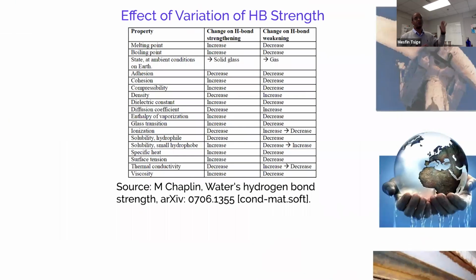So I look at this both on the fundamental side and on the technology side and connect this back to hydrogen bonding. In the case of hydrogen bonding, if we come up with a mechanism of, let's say, increasing the hydrogen bond strengths, then that's going to increase the melting point. We really don't want to do that. But can we come up with ways in which we can actually make the hydrogen bonds slightly weaker, which means decrease the melting temperature, so that instead of melting at 0 degrees centigrade, can we shift it down to -5, -10 degrees centigrade? Those are the kind of surfaces we'll be looking at.